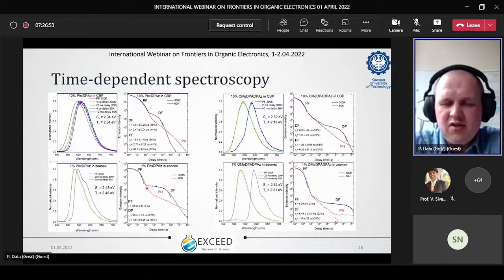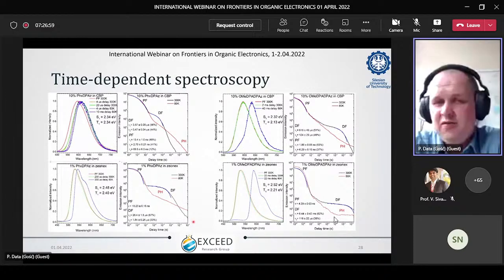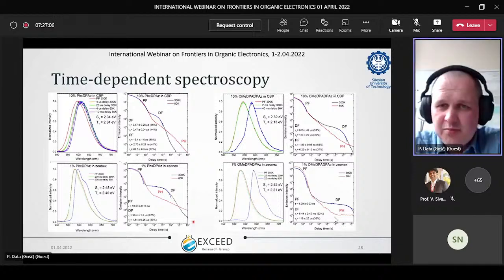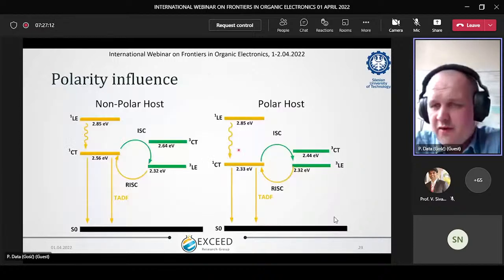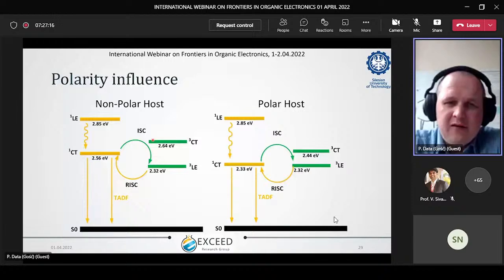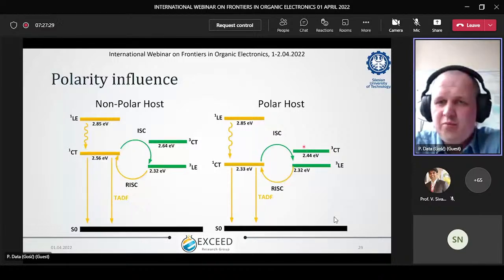Higher delayed fluorescence contribution, so you have higher efficiency, and in the end you have more efficient emitters. So you see that by simply changing the host, we are affecting our molecule, our charge transfer state, and our final efficiency of the device. Like I said, in the non-polar host, we have a high charge transfer state, doesn't matter if that's the singlet excited state or triplet excited state. If we put that into the high polarity host, then we are dropping our energy. Our localized excited states are not affected, but we are affecting our charge transfer state.